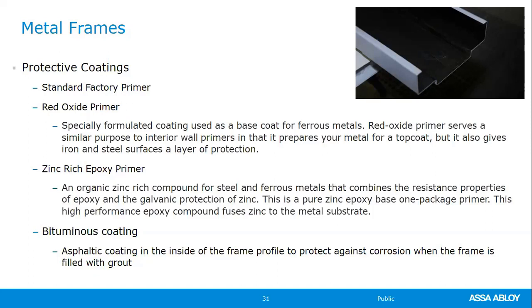Bituminous coating is the detail there at the top right. Years ago, probably 10 or 12 years ago, if you looked at a specification and it called for bituminous coating on these frames because they're going to be grouted, they wanted some sort of coating in the back of the frame to help slow the rust process from the inside out. The factory and the distributor would say that's got to be done in the field. We exclude that from the scope of our bid because that material was so toxic that nobody wanted to touch it. Over the last 7, 8, 9 years, the industry has come out with a water-based, environmentally friendly bituminous coating. It can be used on fire-rated or non-rated frames, 3-sided frames, borrowed lites, sidelights, welded and KD. If you have a shop, your shop guy can actually put this material in the back of the frame to coat it.